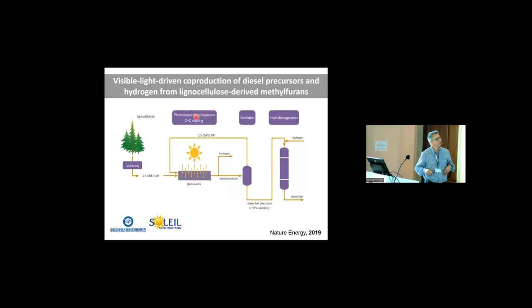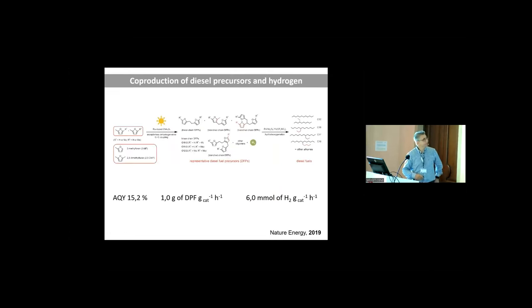The unreacted methyl and dimethyl furans go back to the photoreactor, and then you can use the hydrogen you're producing to make a hydrodeoxygenation reaction, which was the reaction I mentioned to you before, to make diesel. And indeed, with the catalyst we are designing, we were able to make dimers and trimers and oligomers with quite decent apparent quantum yield and a reasonable amount of hydrogen. And the beauty is that you really get good quality diesel fuel with the right branched and linear ratio.